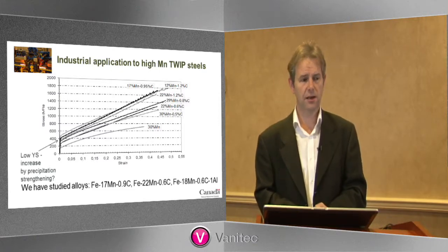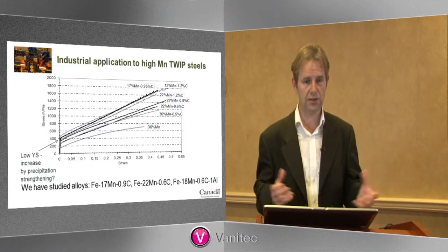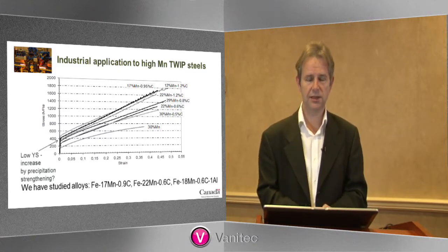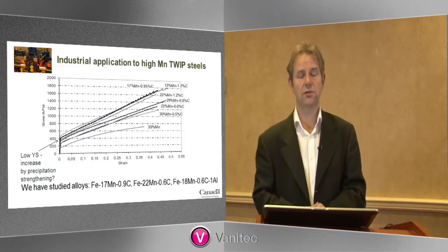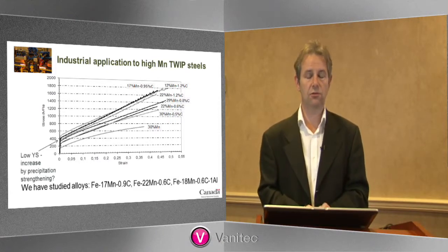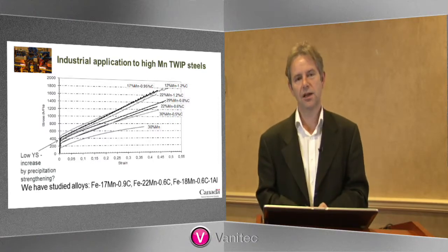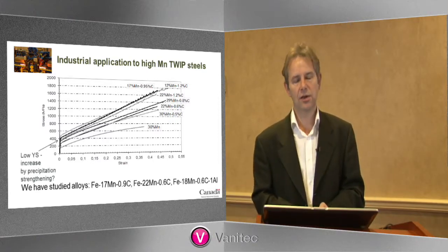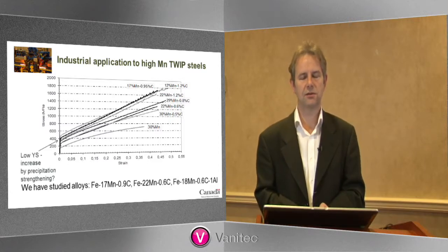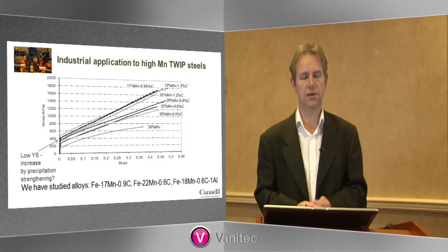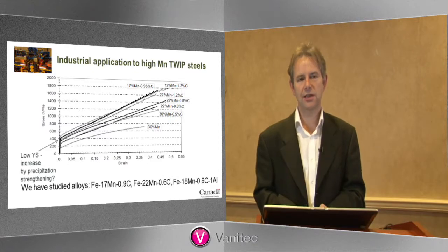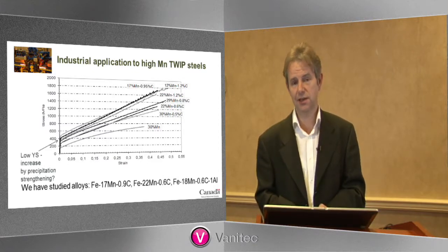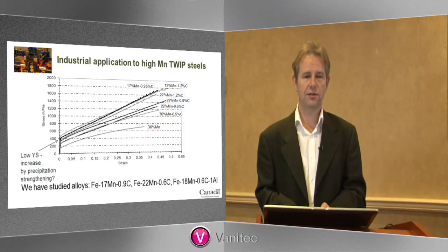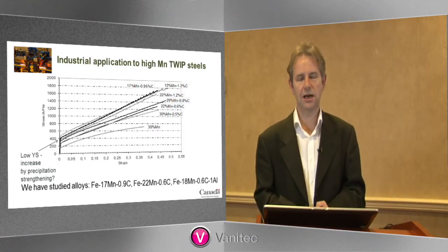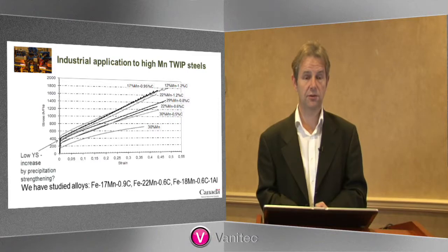Now that could be done in different ways. We can do it by strain hardening, because we actually deform the parts, or we could do it by reducing the grain size, but we hit a technological limit on that, which was due to cold rolling, and you can't really decrease rolling forces. You can't really decrease the grain size below about 3 microns in those steels. It's a technological limit. So it would be very interesting to increase that strength using a different technique, which would be precipitation strengthening. So the question would be, what precipitate would you like to use? And I want to show you that the one that's best to use is vanadium.